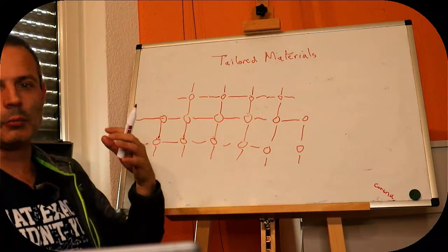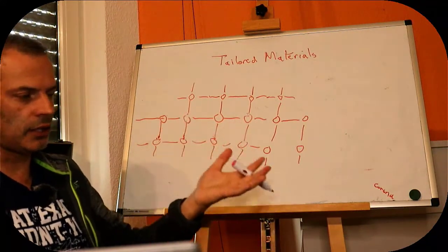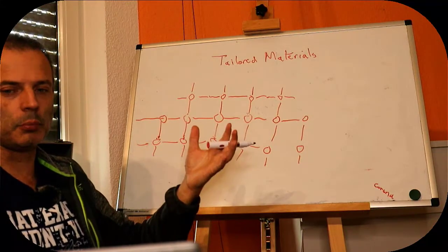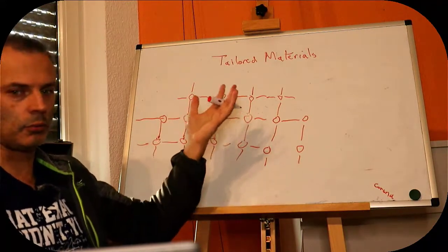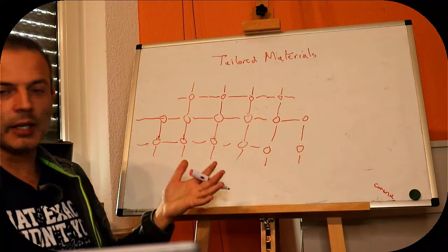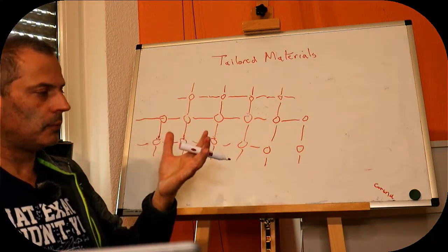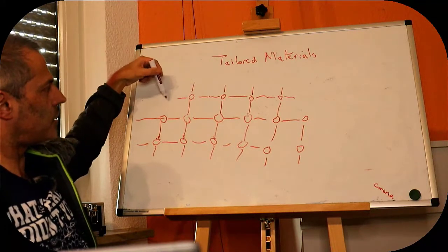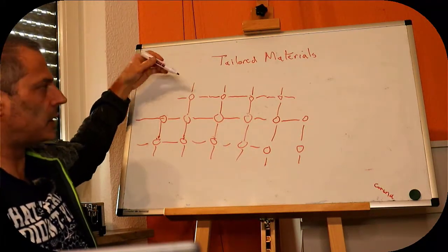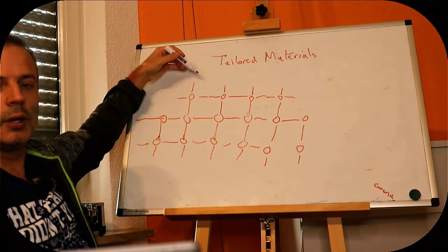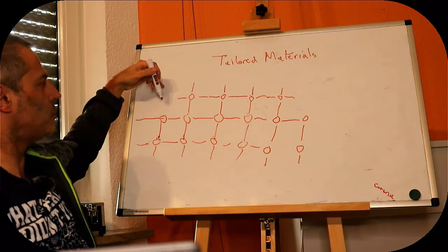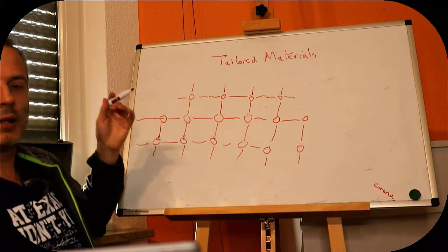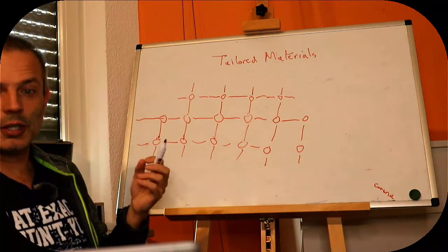If we do it by electrodeposition in a solution, we have to be close to the potential where the metal can dissolve again, because then the molecules can go in and out of the surface until they find a lower energy spot, and then they stay there. The ones that stick out more will fall off, and the ones that stick in more will tend to stay. This gives us different types of crystal growth.